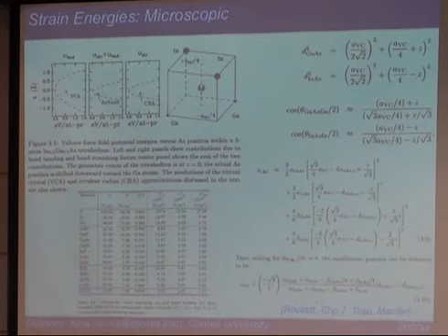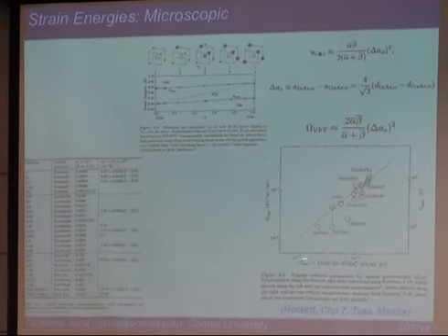You can also calculate them now using first principles DFT, fully from a quantum mechanical perspective. Once you know them, that's extremely useful, and no wonder you get a very good fit between experimentally evaluated energies for this sort of microscopic strain. The experiments and the model are in very good agreement for many classes of III-V alloys.